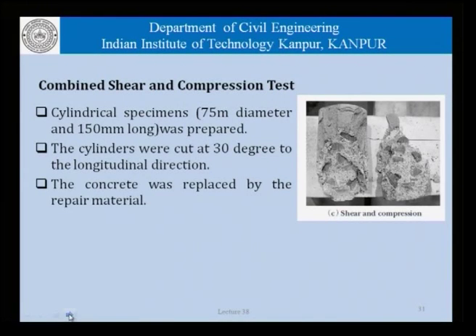When it comes to a combined shear and compression test, a cylindrical specimen 75 millimeters in diameter and 150 mm long was prepared. The cylinders were cut at a slope of 30 degrees to the longitudinal. After whatever surface preparation had to be done, the cylinders were recast using the repair material.